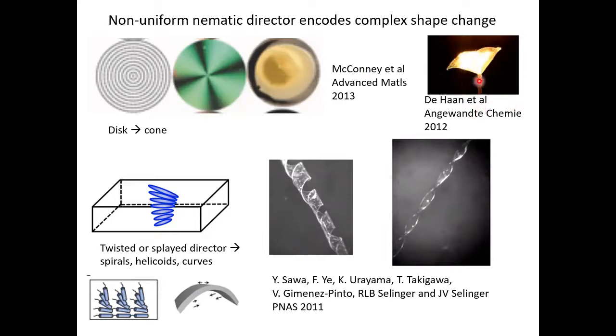Here's another one where the disc has been held onto a thin glass tube, just with a little bit of air suction, and then a heat lamp is shone on it, and it goes from being a disc to looking like a flower. So it's turned into essentially a cone. This shows us that if we have a complex director design, we can get a complex shape change that's not just something simple. Another option is if we have some twist that goes through the thickness of the film, then we can have a flat ribbon that can curl into either a hollow tube or a twisted ribbon. And that happens also with temperature.